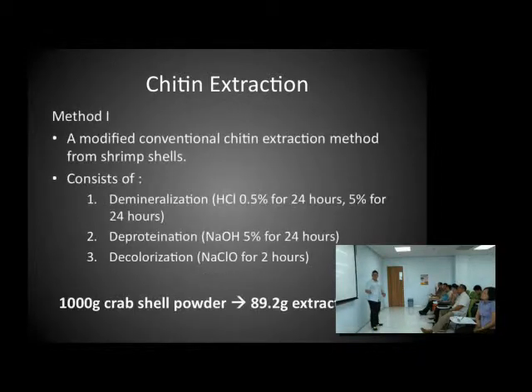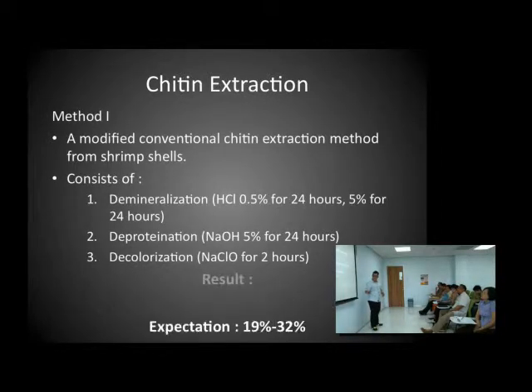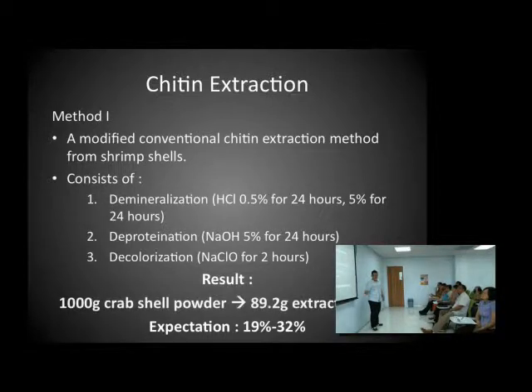Well, the result is that from 1 kilogram of crab shell powder, I obtained about 89.2 grams of chitin extract in solid state. Well, we can see that it's 8.92%, but the expectation is 19 to 32%. So the result is still far below the expectation. Here's how it looks, the solid extract.